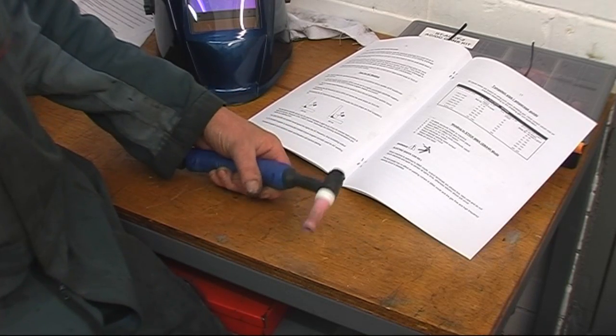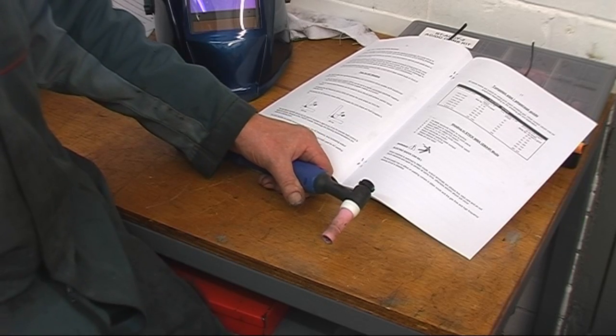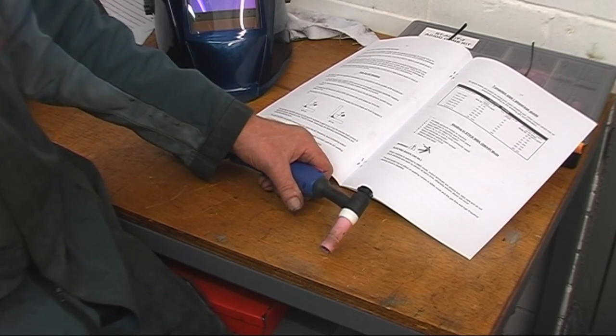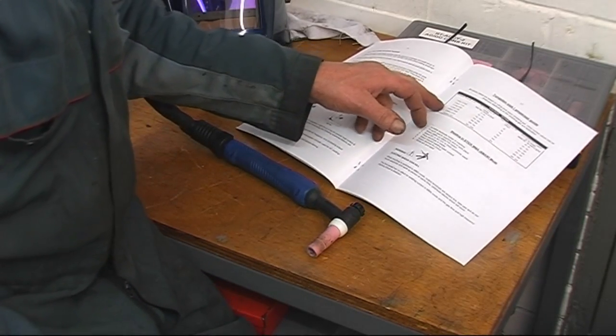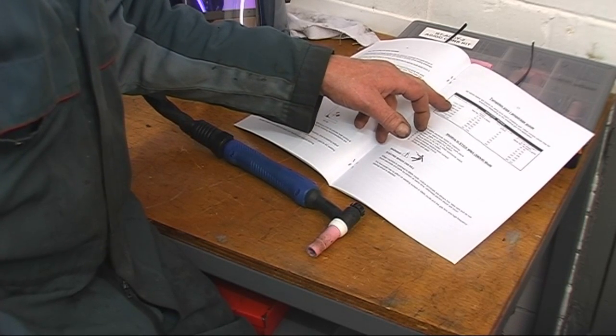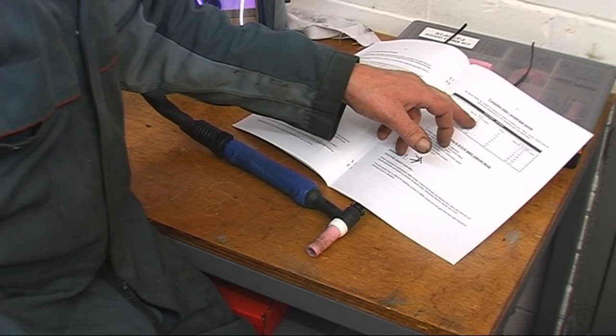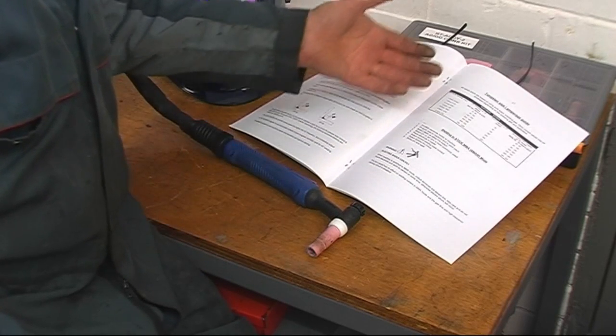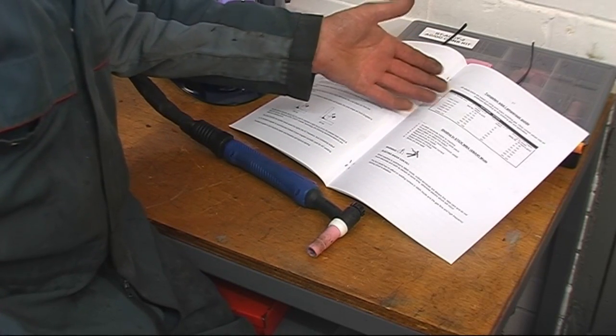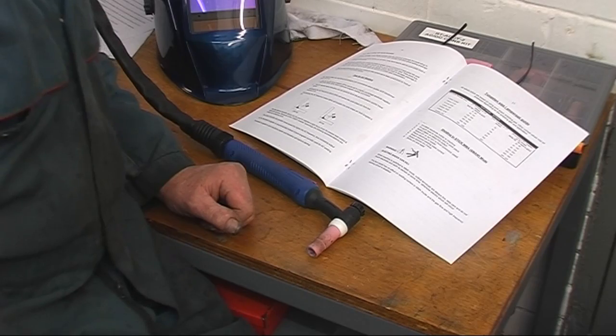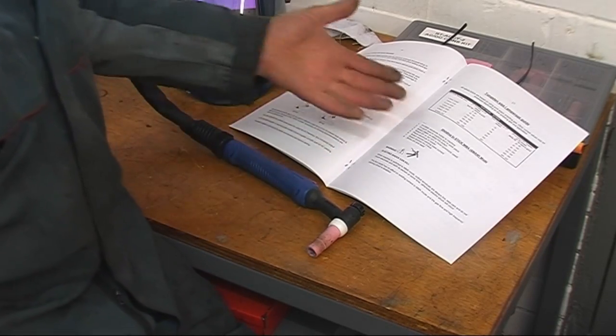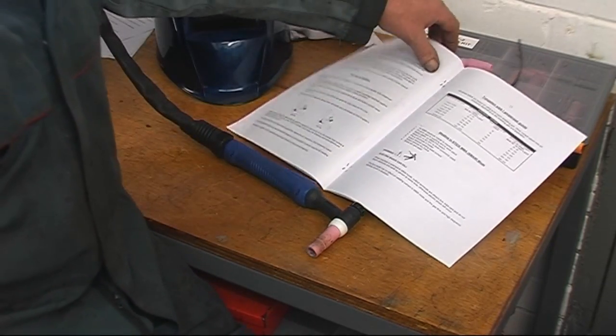We need to set the torch up. Like I say, I'm going to be welding DC, probably around about 100 amps. So there's a little chart, comes with a handbook. It says a 1.6mm tungsten will do 40 to 150 amps on DC. That's a red tungsten, a thoriated tungsten. You use different tungstens on AC for welding aluminium. We'll discuss that when we come to weld aluminium.